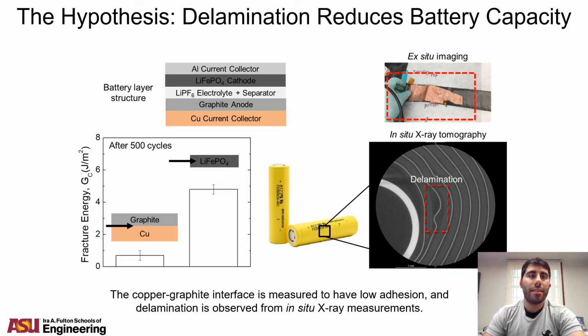And based on our preliminary data, our hypothesis is that a loss of active material due to delamination with cycling could actually contribute significantly to this knee-like effect. And that's primarily because we observe that the adhesion between the graphite anode and the copper current collector is extremely poor, and it goes almost to zero with cycling. And this is corroborated by ex situ imaging when we unroll these batteries, and by in situ X-ray tomography, where we can actually observe the delamination occurring during cycling. And so this indicates a key weak point in commercial cells.